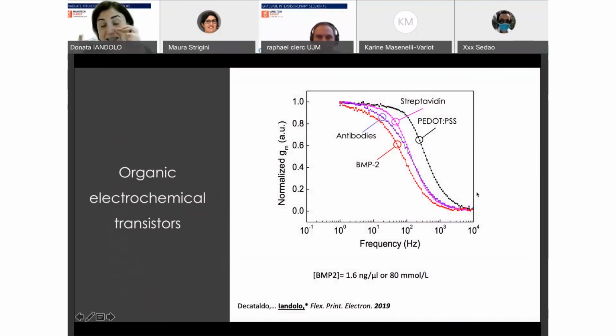True, and you're right. What I showed here is the final characterization of the device. So these measurements would be the gold standard characterization of an OECT. In this case, of course, we have different functionalization strategies reported in the slide, but generally we do two different kinds of measurements. We measure the device performances using different voltages applied across the channel, and different voltages applied at the gate. And so this gives us a certain indication of the performances of the device in general.